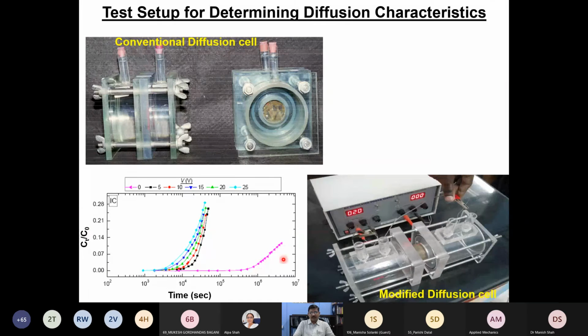Even if you are waiting up to even 10 to the power of -7, the C_t by C naught is not really changing if you do the conventional test like this. But what we did is, we don't want to wait this much time. In addition to the chemical flux, we also applied some amount of electrical flux across the sample. And this is one of my master's students who did this. And then by applying different voltages, we are able to pull the ion from one side to the other side in a very quick fashion.